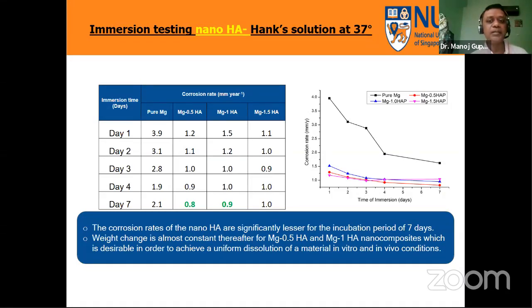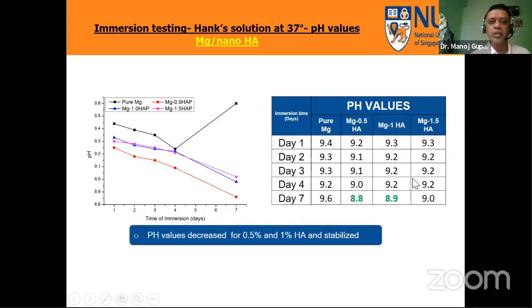Note that if you do the same test in vivo, results have shown that the actual rate of corrosion is almost 1/4 or 1/5 of what you see in the in vitro situation. So these are all acceptable materials from that perspective. If you look at the graph, all these three composite materials are far superior to pure magnesium.